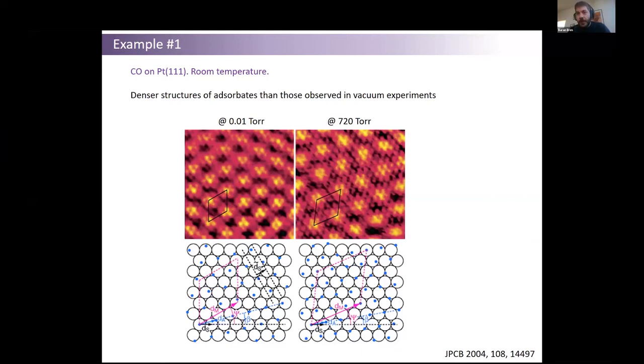It's challenging. You need a surface that's not very mobile, like while working with hydrogen, there are some examples, but water, I didn't see any atomically resolved images. Usually I would say that around 60% of studies are with carbon monoxide, and that's rather easy to atomically resolve.